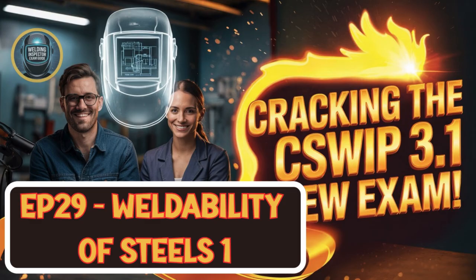Yeah, that crater solidifies last and can easily crack. To avoid those, there are specific techniques. Like with TIG welding, you use current slope out, where the current and the weld pool depth gradually reduce before the arc extinguishes. Gently fades out. Right. Or in manual metal arc welding, stick welding, you might briefly reverse the travel direction right at the end of the run. Just backstep slightly to fill the crater properly before pulling the electrode away. Very effective. Fascinating how the shape of the weld bead, even down to the finish, can be so critical.